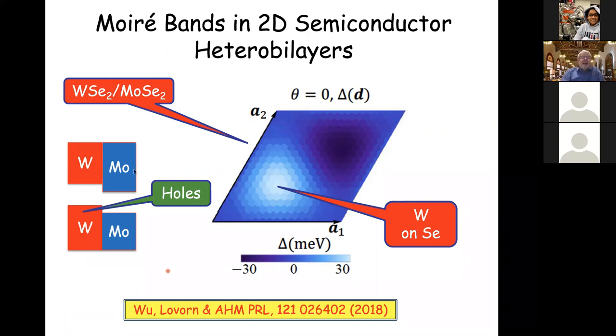And this is the case of transition metal dichalcogenide two-dimensional crystals, a bilayer, one on top of the other. W stands for tungsten diselenide. M stands for molybdenum diselenide. And these two-dimensional crystals have essentially the same lattice constant. You can change the way one two-dimensional crystal is coordinated by the other by simply, for example, twisting the two layers.